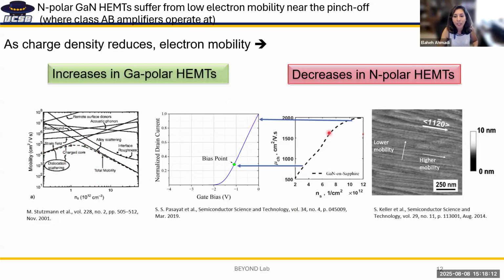We saw that as soon as we start applying negative voltage and going toward the pinch off, the mobility drops very significantly, and around 2E12 near pinch off, the mobility is 500, even though we can get very high mobilities at zero bias. And this matters because, for high efficiency, we want to operate these amplifiers in deep AB class, and that's basically why this low mobility near pinch off can hurt us.